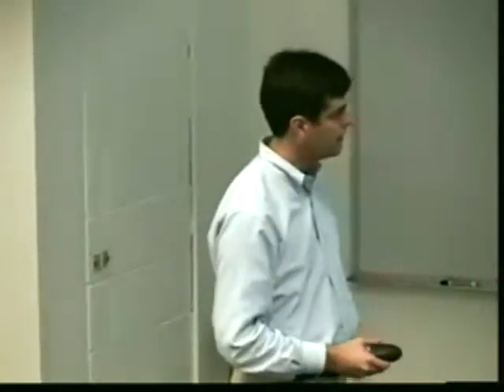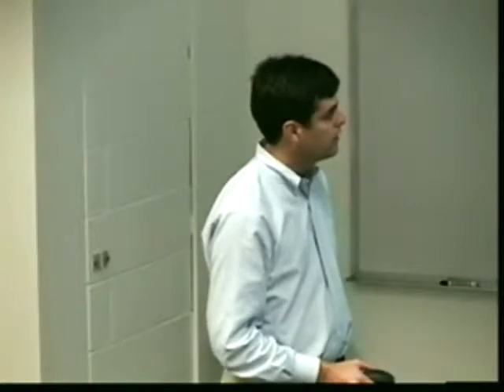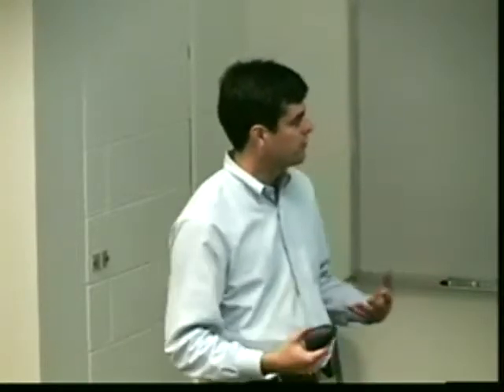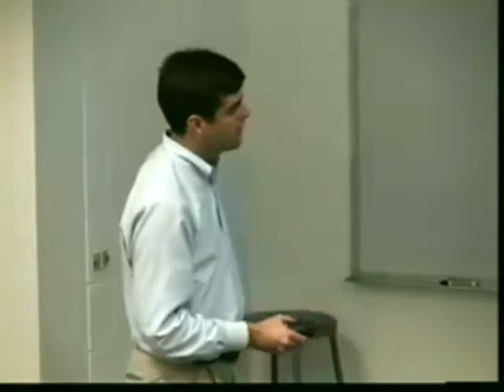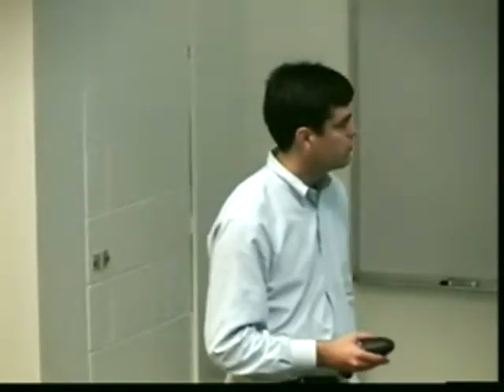This one also has the possibility of adding a small angle scattering detector so that at the same time you're probing lattice spacings, which is a sort of small length scale thing, you can study microstructure to look at grain boundary effects and so forth in the SNS, and you can do that in situ, so you can put on load frames and furnaces and that sort of stuff. It's a very fast diffractometer, so you can do kinetic behavior. In principle, we could do single pulse diffraction, which means you get a pattern every 16.7 milliseconds.